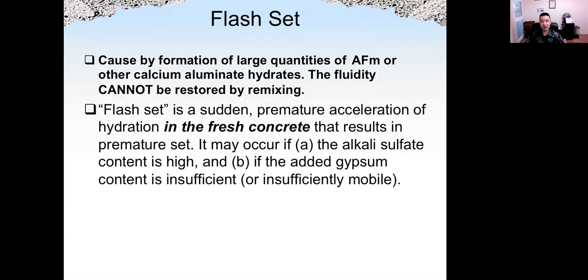For flash set, it is caused by formation of a lot of AFm, or monosulfate. If that's the case, the fluidity cannot be restored by further mixing of the concrete, because we have a formation of AFm. If that's the case, the concrete will set. Remixing the concrete is not helpful. Flash set could be caused either by high alkali sulfate content, or the added gypsum content not being enough. Then we have a formation of AFm.